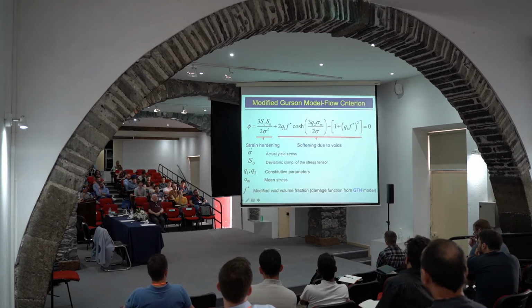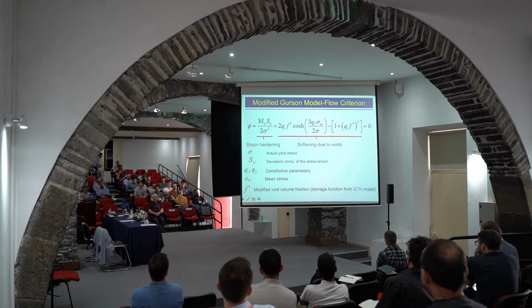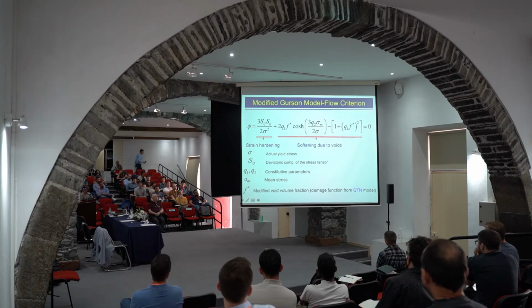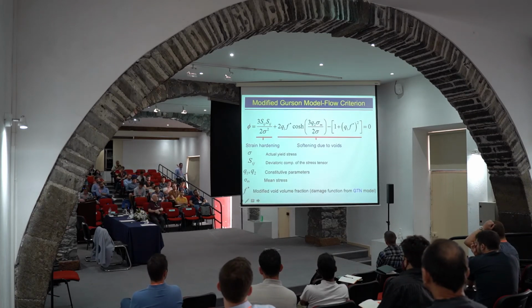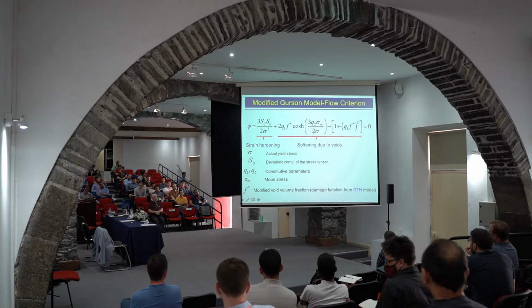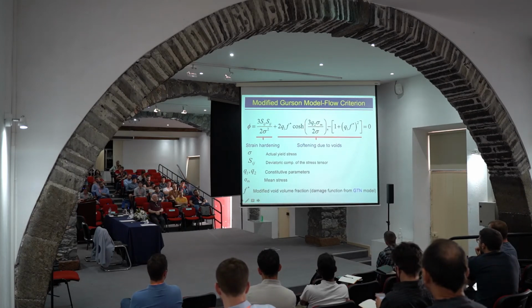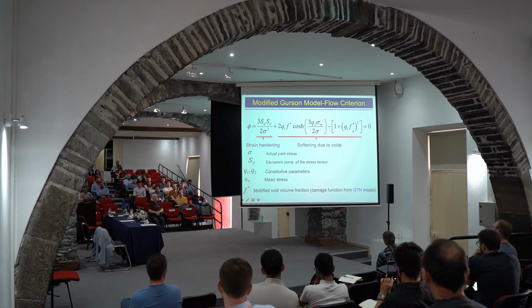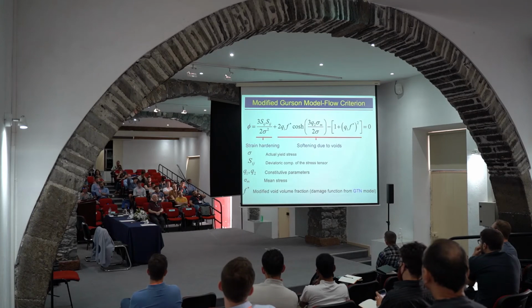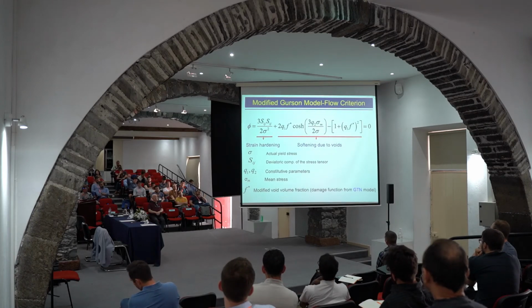So here we have a term which is actually from the Mises yield criterion, and some other terms that try to incorporate material behavior after it gets into plasticity. Once again, we are not dealing with details here, but just pay attention to this volume fraction. This is a very important parameter, this F, and there are many versions of that parameter that I will mention for some details that you will see soon.